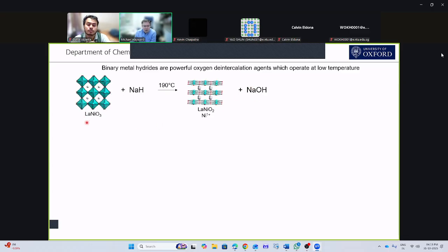Now the reagents we use are binary metal hydrides, and these are really good at extracting oxygen from complex oxides at low temperature. So we have really three reagents we use commonly. The first is sodium hydride. This extracts oxygen from a system to make sodium hydroxide. A good example is LaNiO3 goes to LaNiO2, and we'll have a look at this reaction in just a moment. And now we see that the hydride ion is a 2-electron reducing agent.